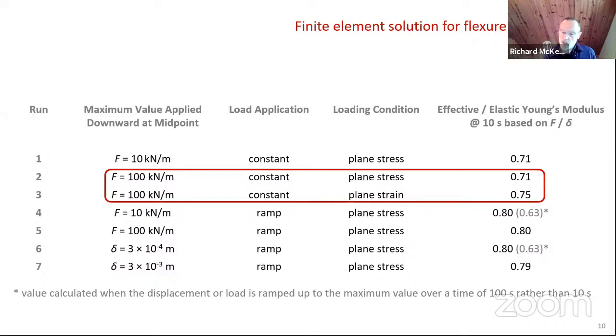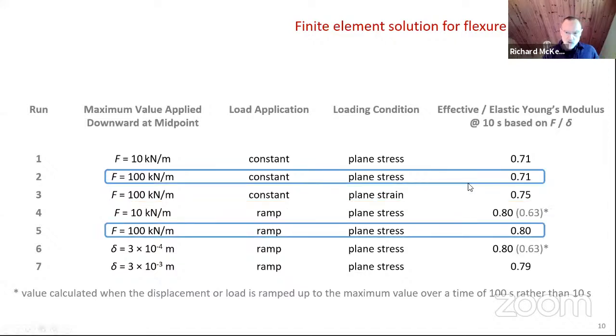So applying the resistance, restraining the beam, makes the beam effectively stiffer. Here, what I've done is I've compared the constant to ramp values, and this is essentially what I showed in the previous two plots, so that you can see the difference in the relative values compared to the elastic values at the end of the 10 seconds.